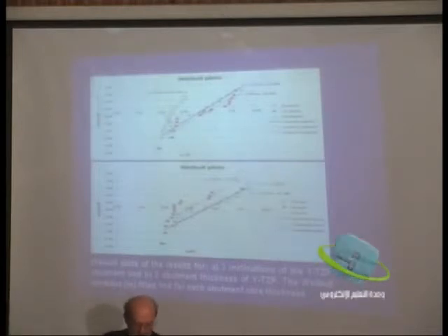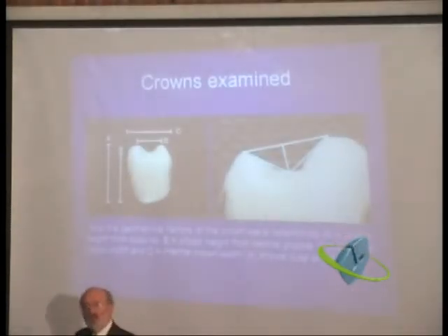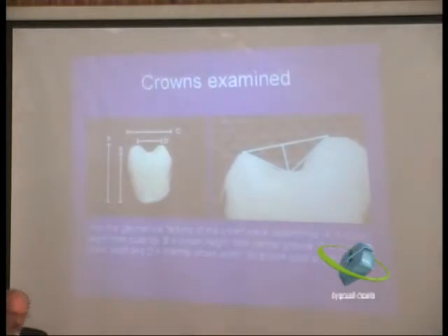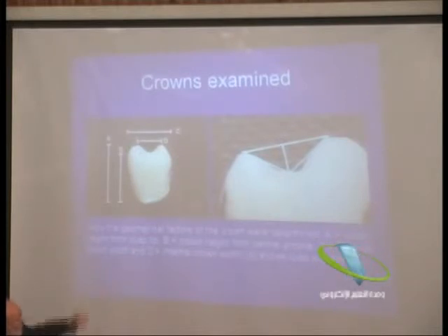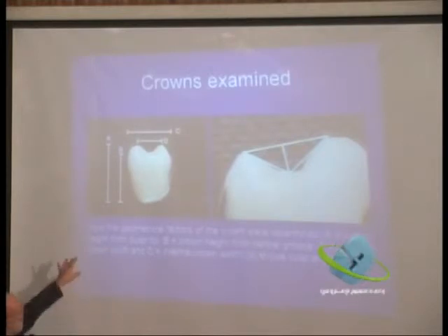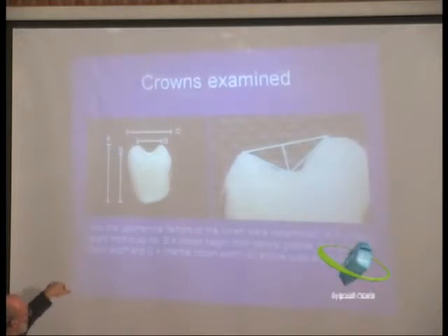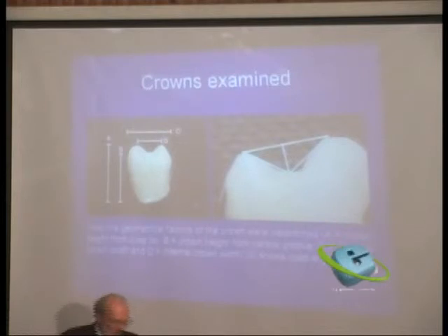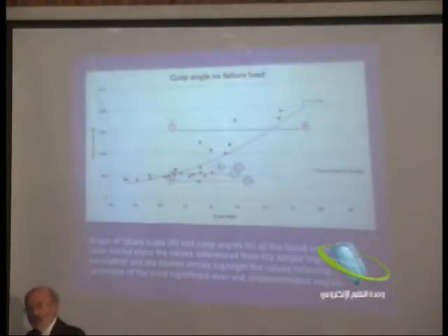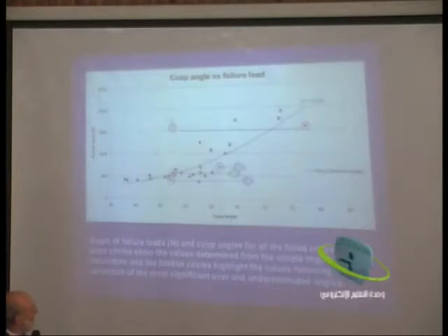So we decided to look at this in another way. We essentially looked at these crowns and said, because they were handmade and there were slight differences between them, we tried to look at them in terms of what is the effect of occlusal angle that is associated with this. And we initially did a very simple process. We just measured the width to the cusp, we measured the height, we measured the depth to the fissure, and on the basis of that, we then looked at all of that data that was generated by these people, and we plotted the failure load against the cusp angle, included cusp angle. And all of a sudden, data that was tremendously scattered began to rationalize more critically.